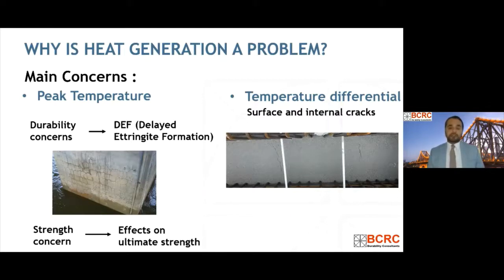With delayed ettringite formation, what happens is that in the later stage, in the hardened concrete, whenever the thermodynamic reaction conditions become favorable, the expansive reactions take place, and you get a lot of random macro cracking, right? And the other effect that we get is the strength concern, which means your ultimate strength might get reduced because of this.